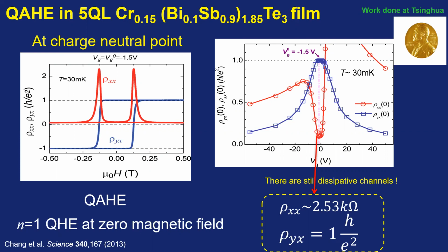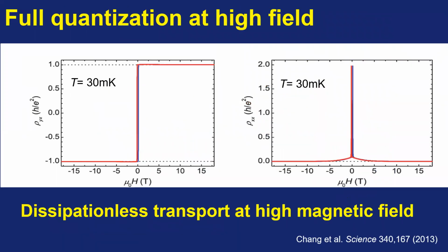So let's see the high magnetic field data. So this is the Hall traces and the longitudinal resistance at a high magnetic field. We can see the Hall resistance is quantized at high magnetic field. The Hall resistance is quantized and the longitudinal resistance exactly goes to 0. So that means at high magnetic field it helps the localization of the dissipative channel in the sample. So we can achieve dissipationless chiral edge transport in this sample at high magnetic field.